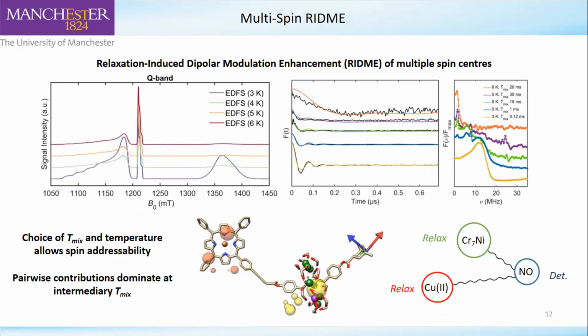But obviously we have 3 spin centers in there, and we wanted to look at doing RIDME of multiple spin centers. And we could play around with both the temperature and this mixing block time in order to choose which interaction we wanted to see, to find excited states of the chromium-7 nickel ring. So we can choose these different temperatures and allow spin addressability based on how we choose our mixing block time